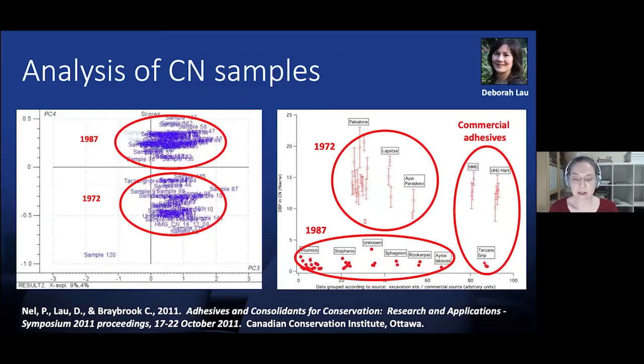A closer analysis of the cellulose nitrate adhesive spectra with specialist multivariate analysis software found that they separated into two clusters associated with the two accession periods of the collection. This was ultimately found to be due to a difference in the concentration of the dibutyl phthalate plasticizer, containing either roughly 2% or 15%, corresponding to the accession periods, and it also correlated with cellulose nitrate-based adhesive formulations. This was all verified using gas chromatography mass spectroscopy.